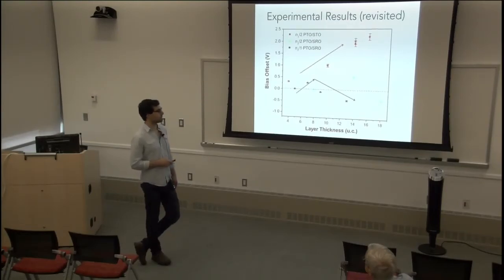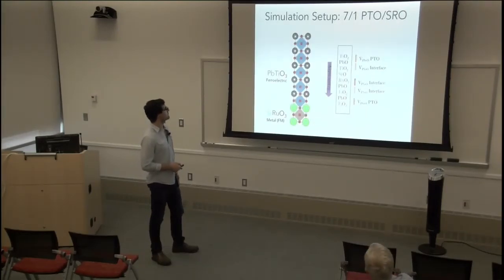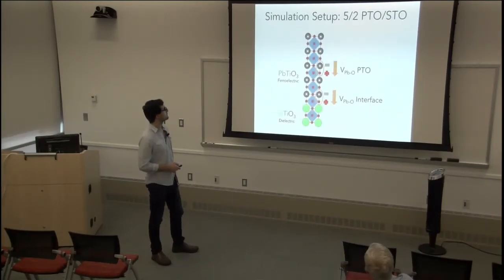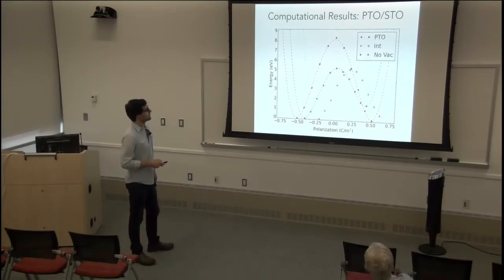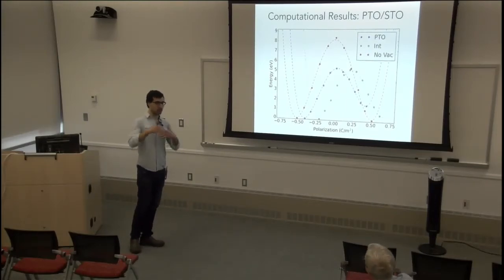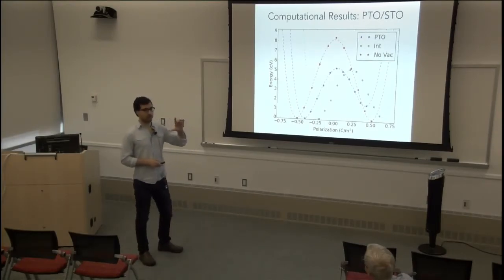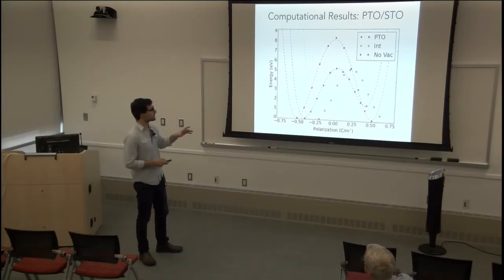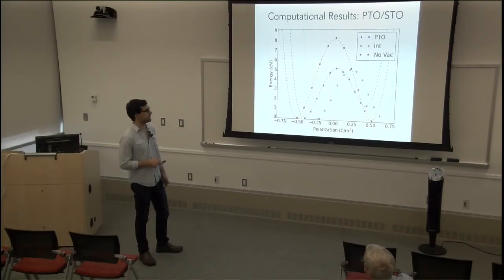what do we have? What we know here is that the asymmetry is much larger for the lead titanate, when the oxygen vacancies in the lead titanate are much higher than for the interface. And as you grow more and more lead titanate, you actually keep the total thickness of the superlattice constant. So as you grow thicker and thicker lead titanate superlattices, there are fewer interfaces and more lead titanate. So the amount of oxygen vacancies in the interfaces decreases, and the amount of oxygen vacancies in the lead titanate increases.